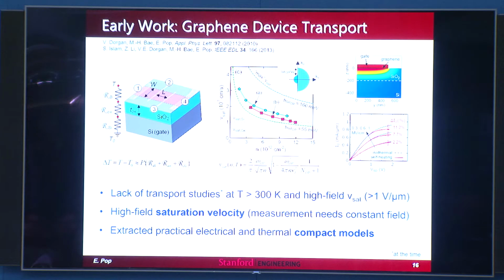In graphene, you have, remember, those Dirac cones that are so elegant. But the fact that you have those Dirac cones is also increasing your density of states for scattering when you go up to higher fields and higher energies. And so that actually leads to this 1 over square root of n dependence that you basically see over here. It's actually captured in that term. This term is actually not really dominant, but that's the term right there. And so you see that from the model directly.